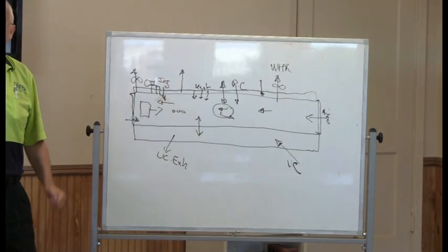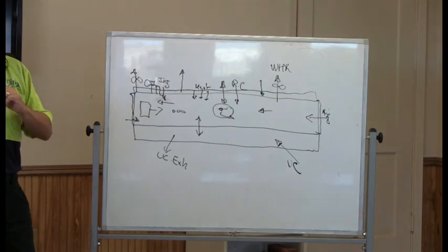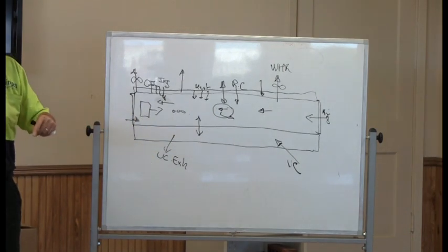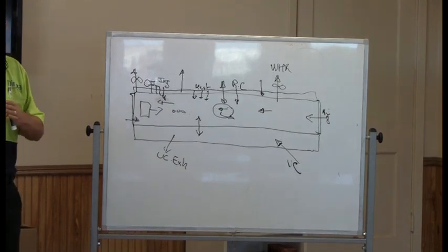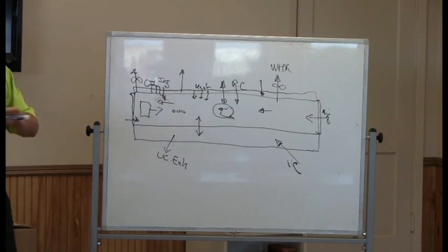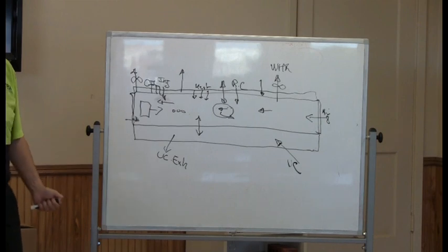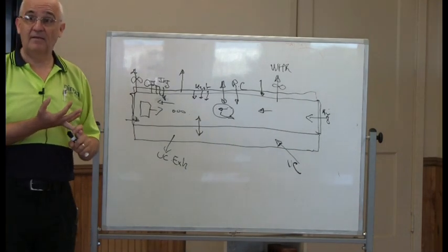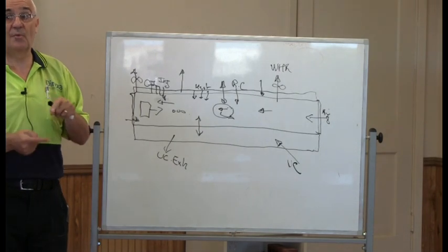On the second visit, when I came back with the booster burner installed, they could not recognize their kiln. The hacks were straighter, the homogeneity was back, everything was great, but the gas was the same. I said, it means that whatever we were bringing to the kiln, we were messing up the kiln and using gas from the kiln. Now we are using gas from the booster and the gas bill didn't change. So for me, it's a win-win situation. You improve the quality and you don't waste energy. And the next step was, the kiln is now ready for burner tune-up, not the other way around.